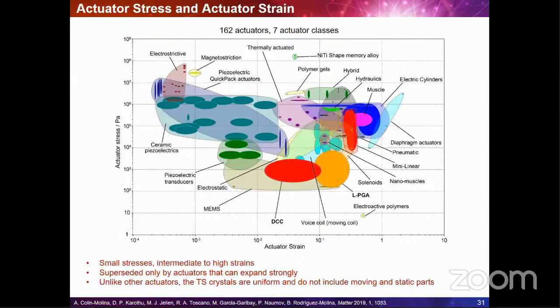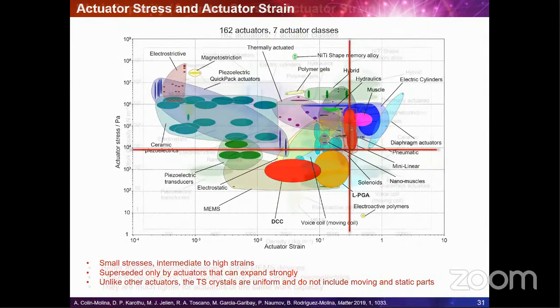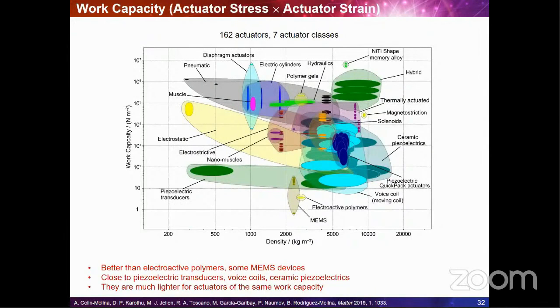So along the same lines, I would like to mention that due to the small size, thermosalient crystals are able to produce very small amounts of work. This is what we actually know, how much work we can get with these materials. However, the work increases by increasing the crystal size. So they have a higher work capacity than electroactive polymers and some MEMS-based devices, and they perform close to piezoelectric transducers, voice coils, and some ceramic piezoelectrics.